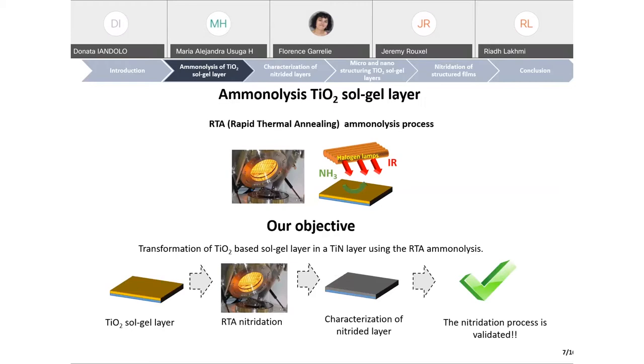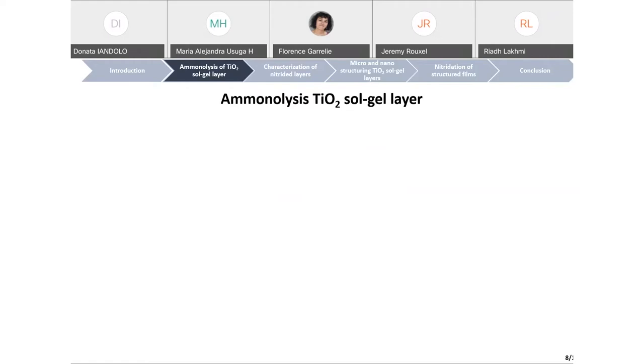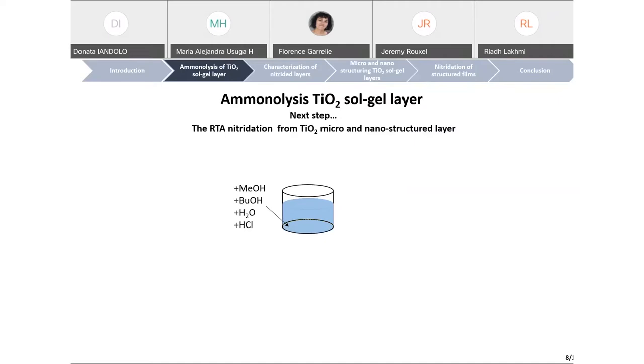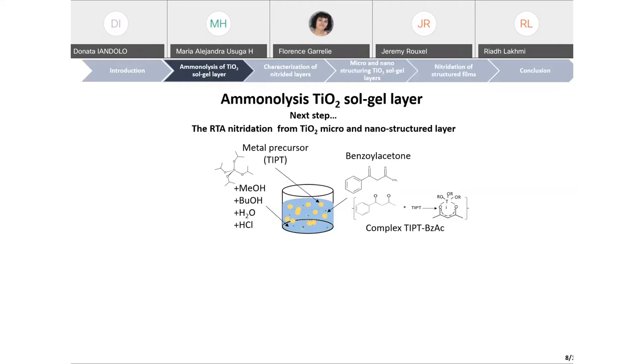To realize the micro and nanostructures, it is necessary to employ the photosensitive properties of the sol-gel. To obtain a photopatternable sol-gel, it is necessary to mix some solvents like methanol, butanol, water, and hydrochloric acid as catalyzer, a metal precursor, titanium isopropoxide, and a complex agent, benzoyl acetone. The titanium isopropoxide and benzoyl acetone form a complex which is photosensitive to UV light.